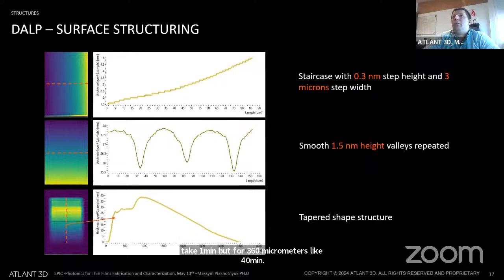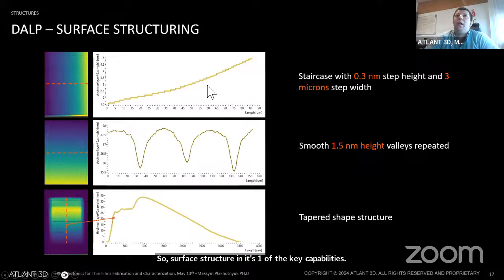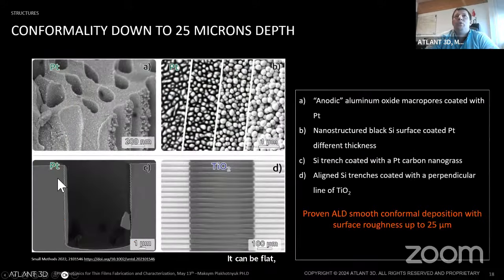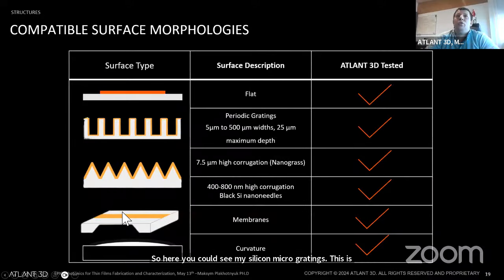So surface structuring, it's one of the key capabilities. So here you could see step-like gradient. It can be flat gradient, so very straight, or this type of structures. We can deposit over different type of surfaces. So here you could see silicon microgratings. This is black silicon. This is porous material. And this is just overview what type of surfaces we already deposited on. So random micro, like membranes, or curved surfaces like for optics.